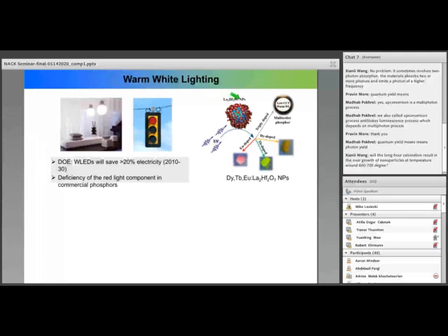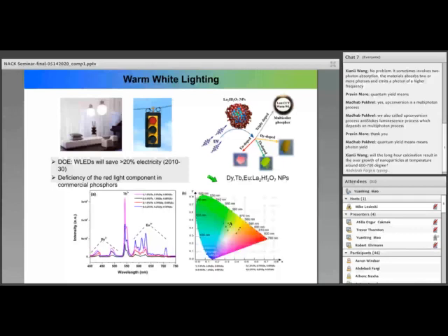So what we did is actually still based on this type of composition, but we triply doped them to get this type of phosphor. And it has many advantages, because now all the dopants are actually in one host, instead of having these different components, making powders of each of the singly doped ones, and then mixing them, right? So with this triply doped one, the energy transfer between the dopants can also happen. So that is what we see here.